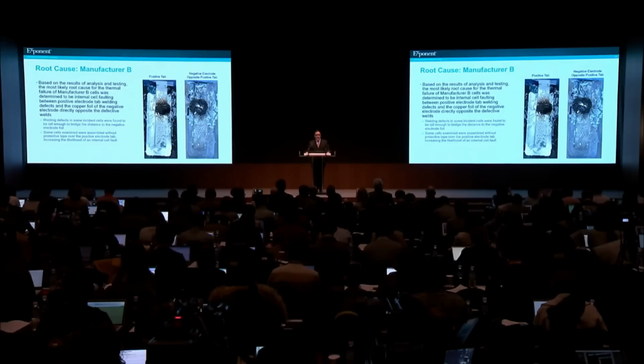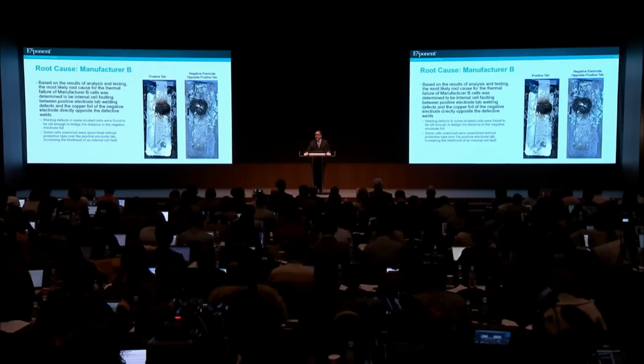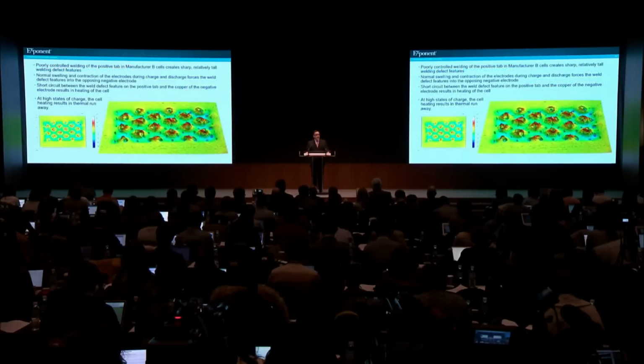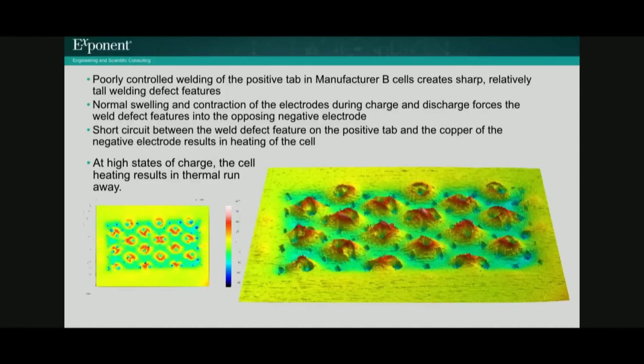Further, it can be seen that the pressure within the cell was high enough that an impression of the ultrasonic weld pattern was transferred to the surface of the negative electrode. All of these observations support the notion that a short circuit can be established between a weld defect on the positive tab and the opposing negative electrode. The images on this slide show two-dimensional and three-dimensional profilometry data for the lower set of welds on the tab that was shown in the last slide. In these data, warmer colors correspond to higher height measurements. The data shows welding defects are relatively tall and sharp.